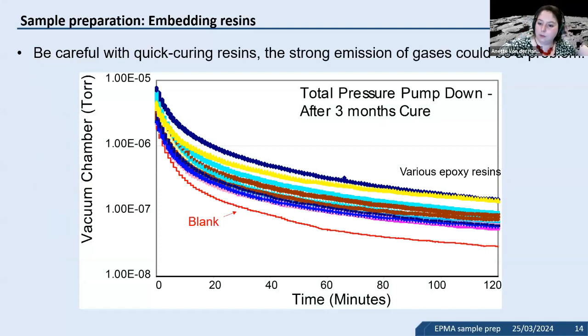Specifically with resins, they are not created equal, especially when it comes to the emission of gas. Usually I find that the more quick curing it is, like if it's advertised as set in 30 minutes, it usually means that it also has a strong emission of gases later, and can be a real problem with pump down time in a scanning electron microscope or an electron microprobe.